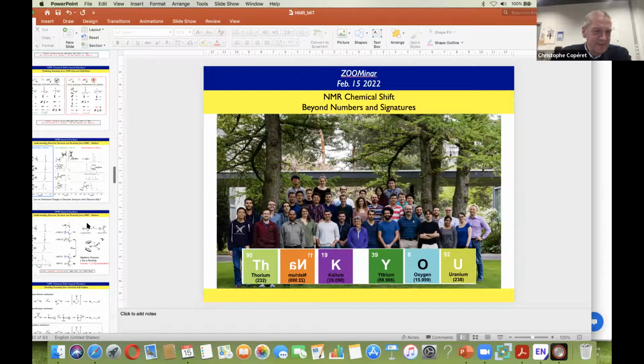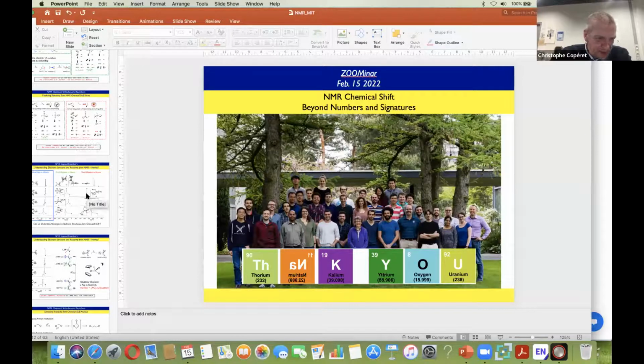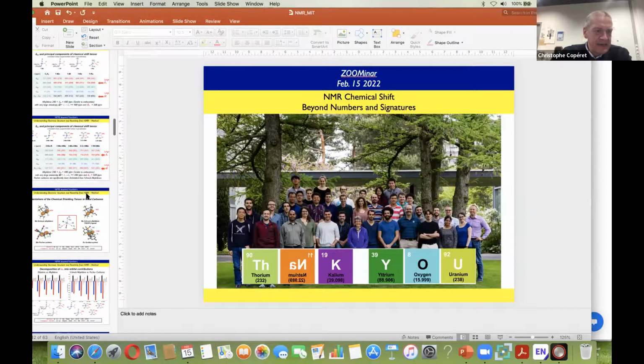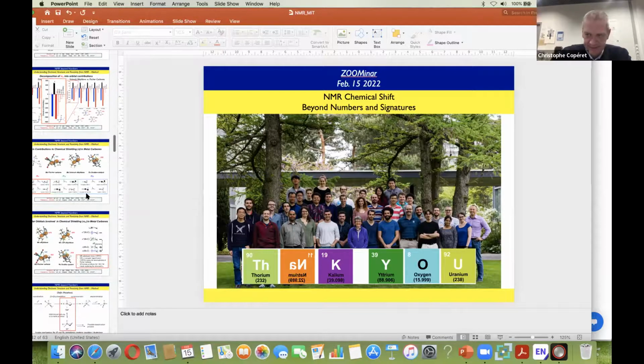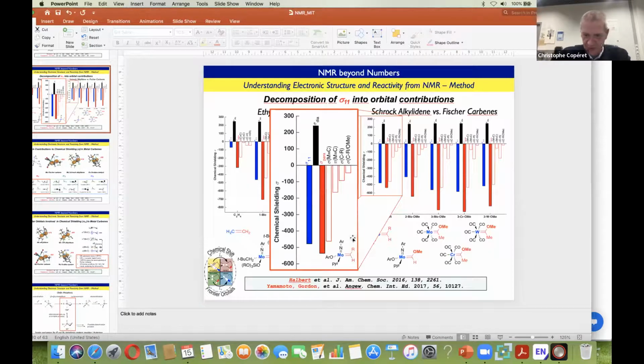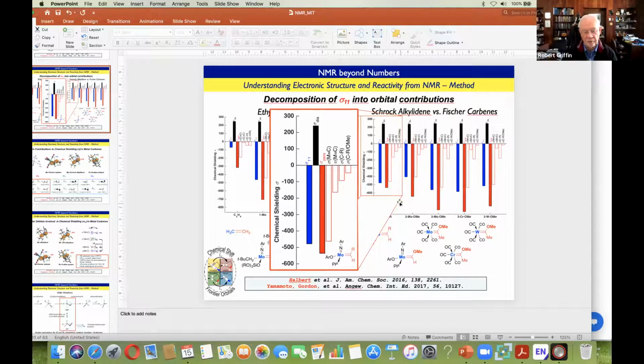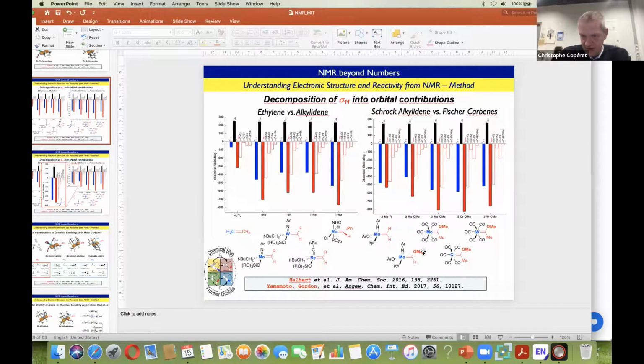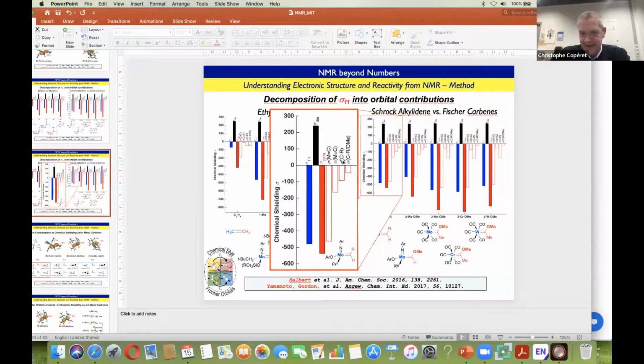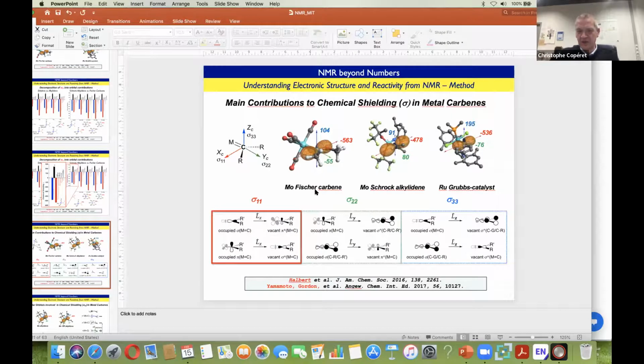Typically in the case of metal complexes, maybe I should put my presentation back on. Do you see my screen again? Yes. Typically we see that in most metal complexes, it's actually sigma 1,1. But in one specific case, and I will not have the data here, in the case of the ruthenium catalyst, the Grubbs complex, both 1,1 and 2,2 are moving. It depends on who is contributing. As I told you earlier in that slide, it depends very much on who is contributing to sigma 2,2. If you look at this orbital here, sigma 2,2 is driven mainly by this connection between the filled pi and basically another sigma of the CH.